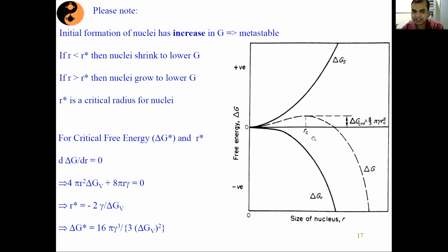So if you stop your deposition somewhere here, then we know that any movement of any process direction is governed by that in which direction its energy is lowered. So you can see here that for this point, the energy is lowered if it further lowers its radius. So what does that mean? That nucleation whose dimension is below RC will try to lower its energy by further shrinking itself, or by further breaking itself into smaller pieces. That is why I said that any nucleation will be stable only once it has crossed a critical radius, and that critical radius is given by this RC.